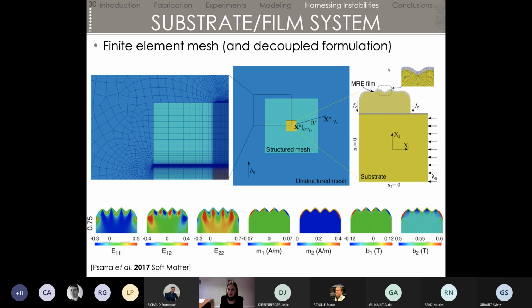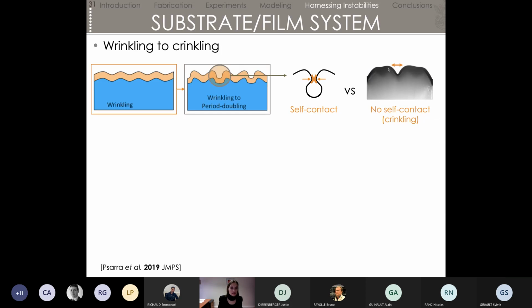The only interest of bothering doing that is that we have access via the finite element to quantities that we cannot measure experimentally. So namely deformation inside the film and also all the magnetic quantities. And that was very useful to develop this finite element model, because, as I said before, when you compress too much, you have secondary instability. So you go from wrinkling, which is those waves, and if you keep doing it, you're gonna get period doubling and so on. And when you have period doubling just in mechanics, you will have self-contact between those two ridges. And we did not see that on our sample under magnetic field.